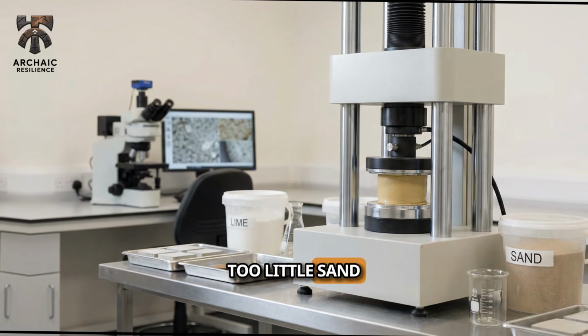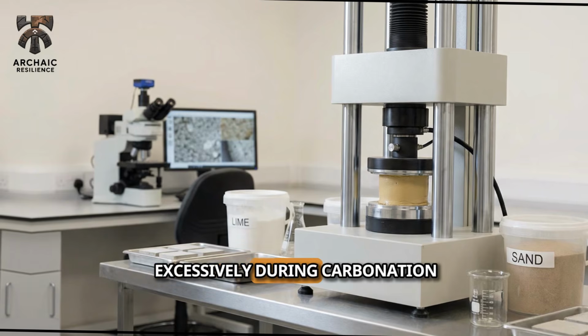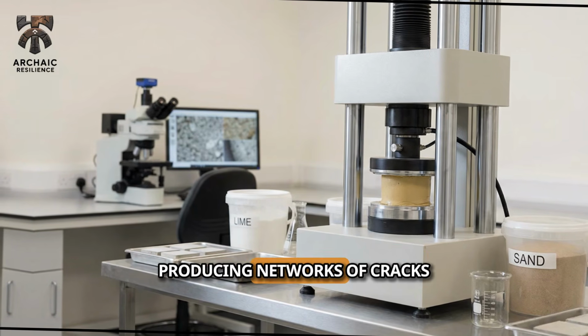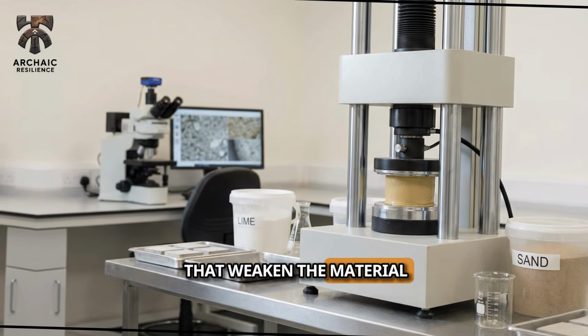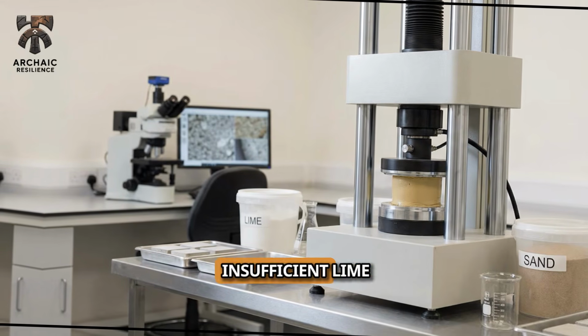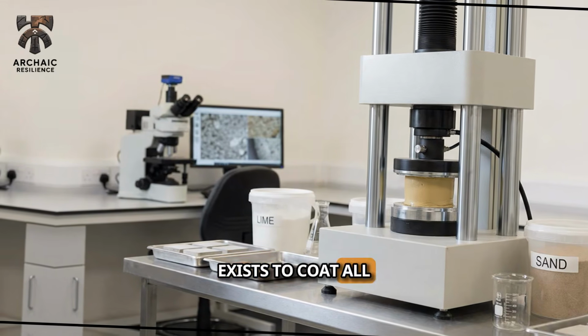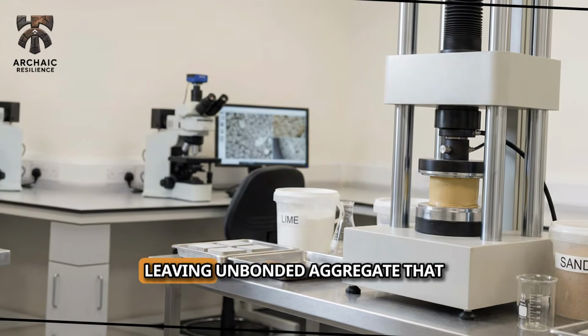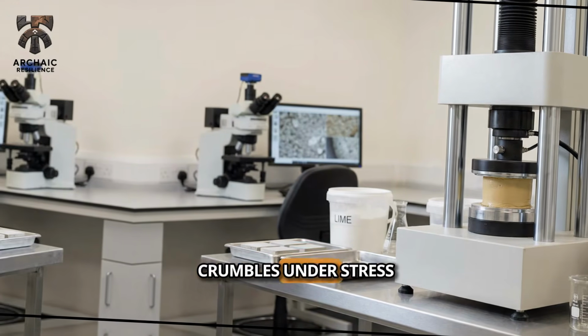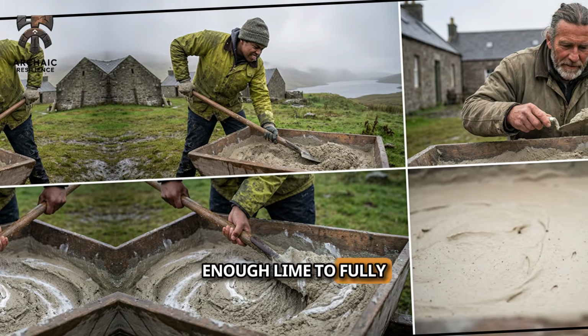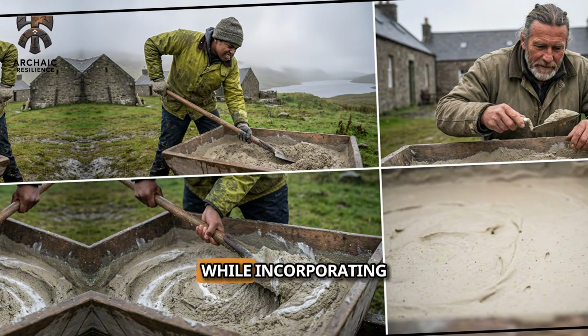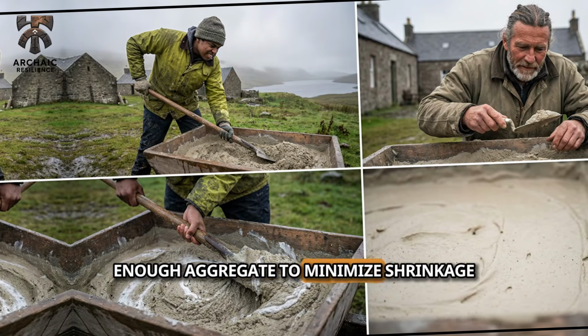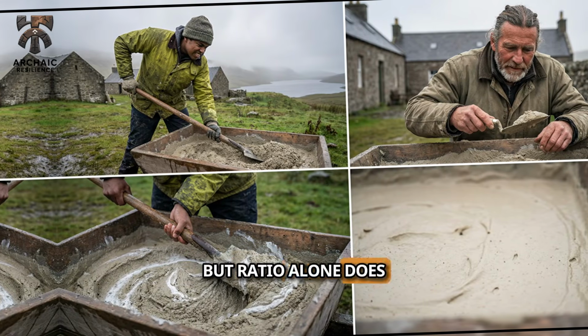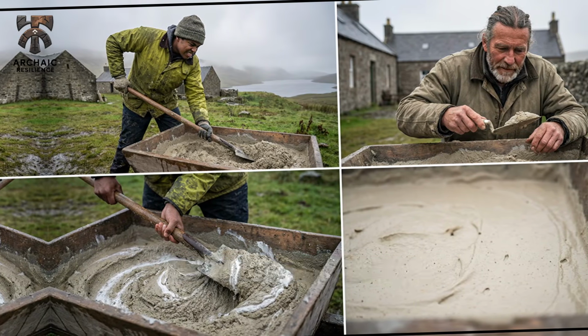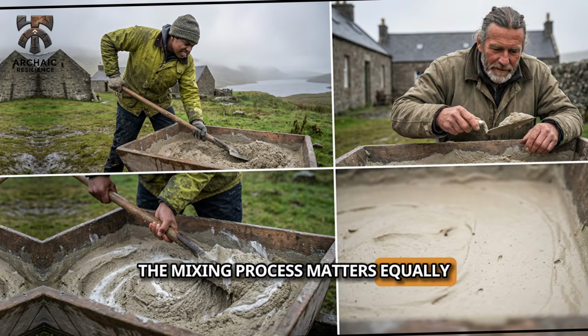Too little sand, and the mortar shrinks excessively during carbonation, producing networks of cracks that weaken the material. Too much sand and insufficient lime exists to coat all particle surfaces, leaving unbonded aggregate that crumbles under stress. The 1:3 ratio provides enough lime to fully surround every sand grain, while incorporating enough aggregate to minimize shrinkage. But ratio alone does not produce quality mortar. The mixing process matters equally.